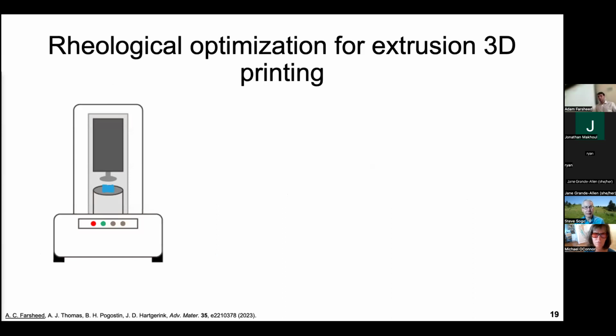And so switching into a technique that we use for the material optimization, this is a beautiful schematic of a rheometer. And what this is designed to do is help us understand the properties of these gel-like materials. And so this is what we use to understand the viscoelastic properties of the materials that we work with. And just briefly, the way that it works is you have a gel that's then compressed between two plates, and then those plates will rotate back and forth.